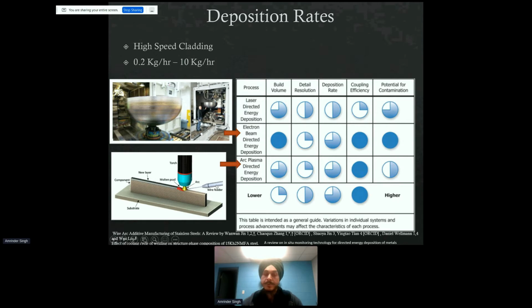And this is all computer controlled. In this one we can have a layer of 40 thou, and the deposition rate can be as high as 10 kg per hour. Now, if we need only a thin layer, and it has to be faster, we can do that too. We can use our powder flow process and still have very, very high speeds of pretty much 1,000 millimeters per second.